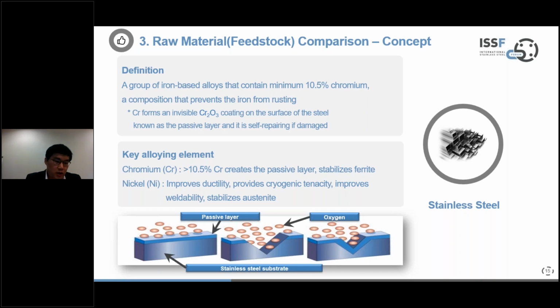You can see on the picture below that we have the stainless steel substrate. We have the passive layer, which is created by this chromium, that prevents the stainless steel from being exposed to oxygen, thus makes the material stainless. From this, we can see that the key alloy elements are, of course, chromium, but also nickel. And nickel, if you add it, improves ductility, provides cryogenic tenacity, improves weldability, and stabilizes austenite.